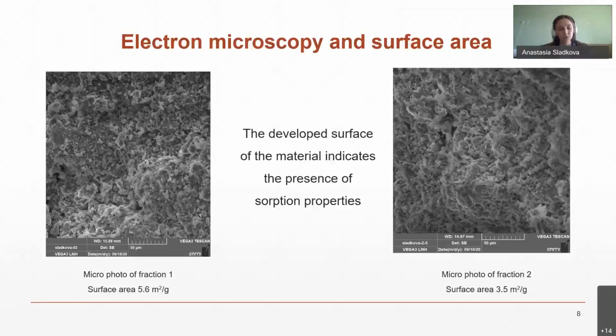Natural and artificial materials used as sorbents have a significantly higher surface area than the slag. The area of such sorbents can range from 30 to 1,500 square meters per gram. But materials used for selective sorption, such as iron shavings, can have a surface area from 15 to 58 square centimeters per gram. Therefore, it can be assumed that the slag can sorb certain substances from solutions.